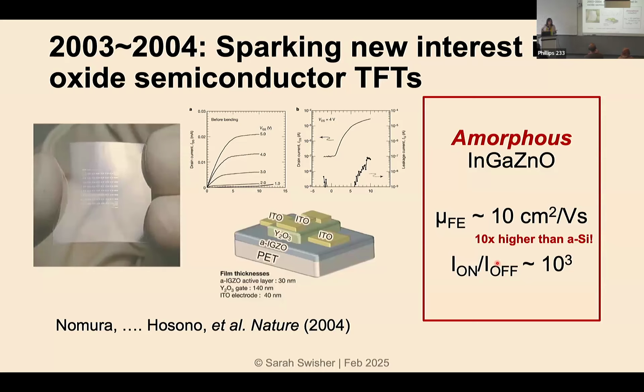So with silicon, we know that if you go from crystalline silicon to amorphous silicon, your mobility drops from a few hundred to maybe 1 centimeter squared per volt second, right? So this is already 10 times better than amorphous silicon, but it has all the benefits of an amorphous film. So for those of you who are more used to working with crystalline materials, amorphous films have a lot of benefits for very large area electronics because you can get a more uniform film over a very large area.